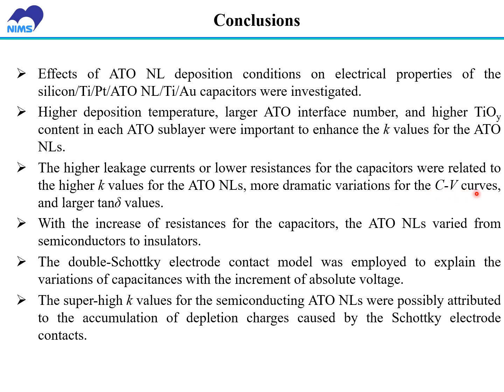More dramatic variation of the CV curves and larger loss tangent values were also observed. With the increase of resistance for the capacitors, the ATO nanolaminates varied from semiconductors to insulators. The double Schottky electrode contact model was employed to explain the variation of capacitance with the increment of the absolute voltage. The super high K value for the semiconducting ATO nanolaminate was possibly attributed to the accumulation of depletion charge caused by the